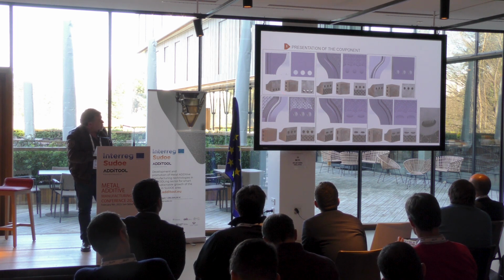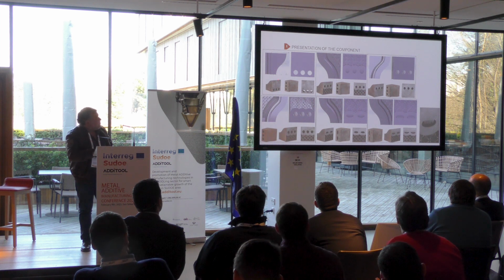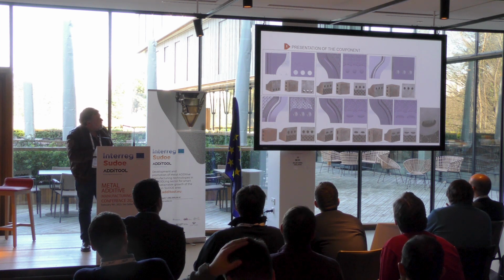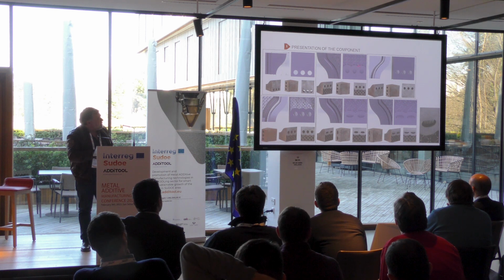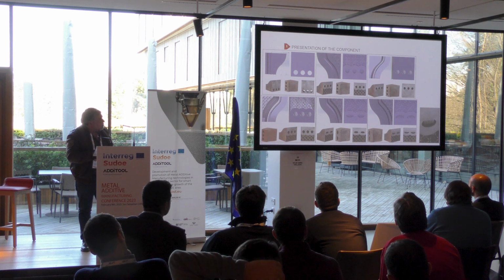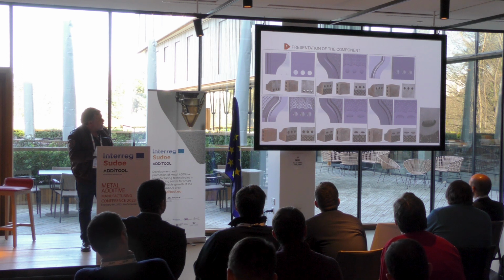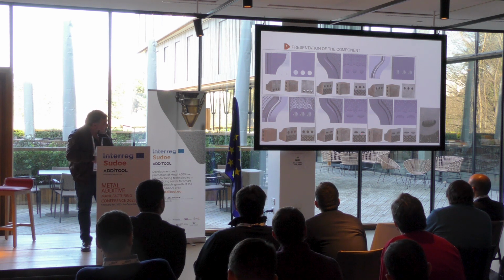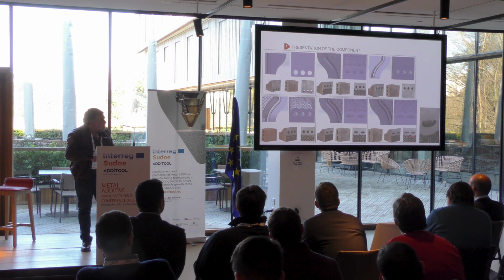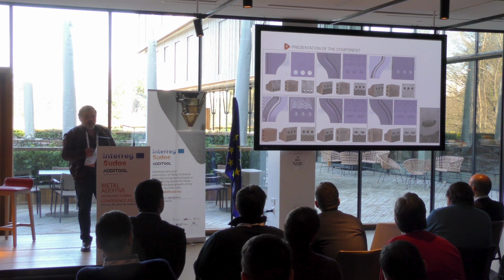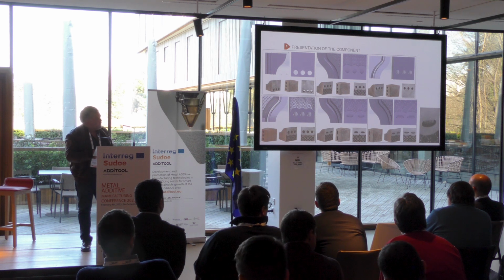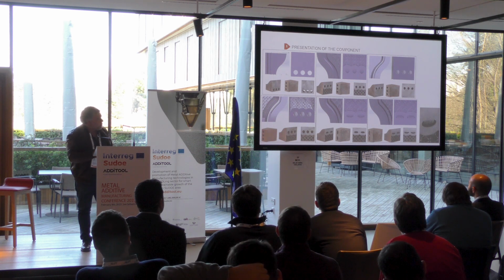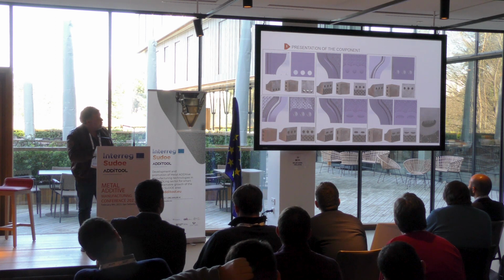I could show that we started with this conventional design. Then we also used the lattice and the circular shapes, changing the diameter to provide different velocity profiles. We also went to elliptical shapes, without and with some fins, to try to see the influence of shape in the conformal cooling rate.